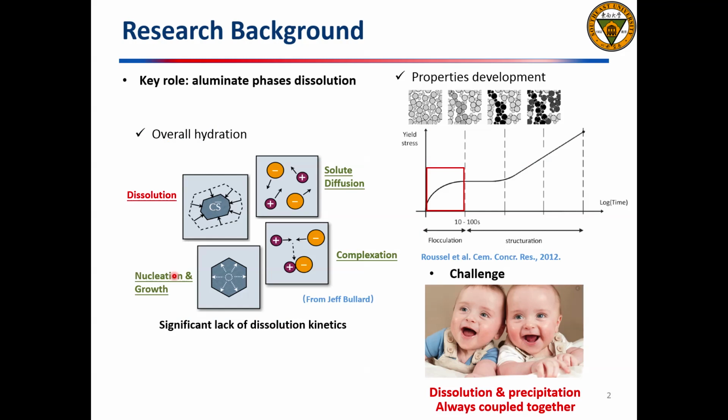Despite many remarkable efforts spent on understanding the reaction kinetics of cement, the lack of knowledge on C3A dissolution kinetics remains a challenge due to its extremely high reactivity. Normally, dissolution and precipitation are always coupled together like twins, making it difficult to study C3A dissolution alone. Fortunately, with the development of holography, we are able to catch the initial time window of pure dissolution of C3A.